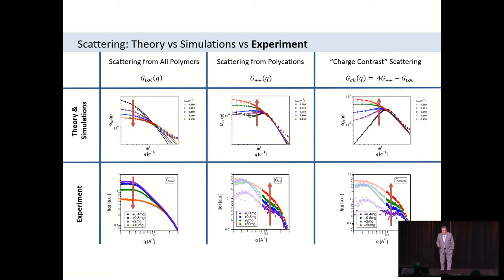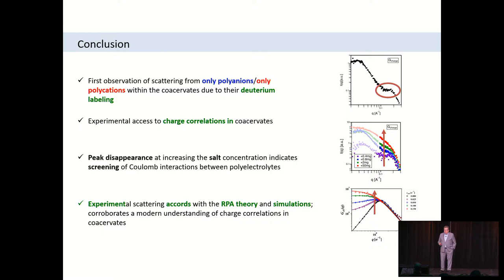So we think this is one of the first times that one has observed scattering from only the polyanions in a polyanion-polycation mixture by deuterium labeling. And as expected in the middle curve there, that peak in the lowest curve in the middle goes away when you add salt. Okay,